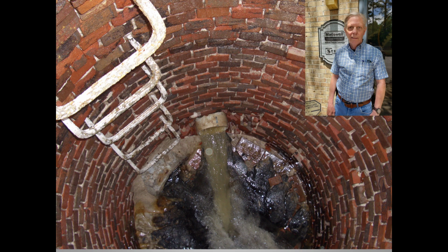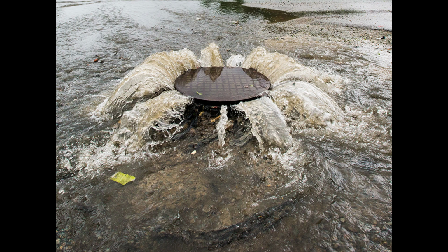The picture you see here is obviously of a brick manhole with steps in it, and as many of the manholes that exist in Ross Valley are under this same condition, they experience a high level of microbial influenced corrosion, and that causes the mortar between the bricks to deteriorate, causes them to get loose, to leak, in some cases fall out, and this allows inflow and infiltration, which John Vogel said earlier caused nightmares for Ross Valley back in the day. They're starting to get this under control now.